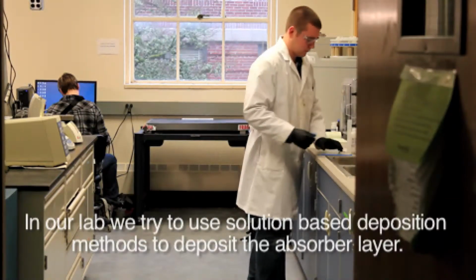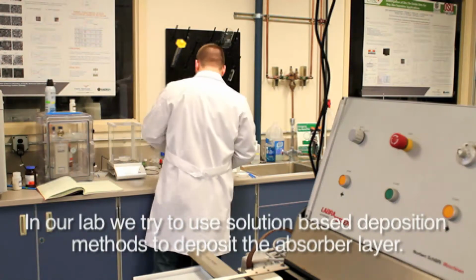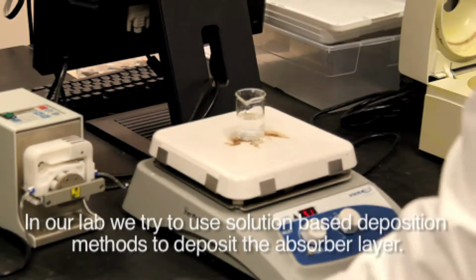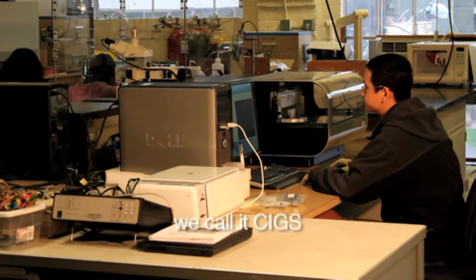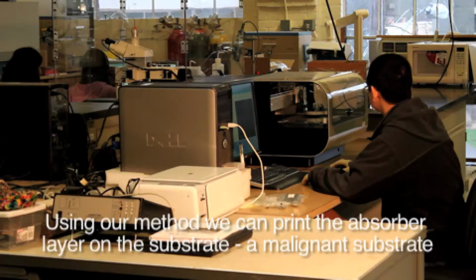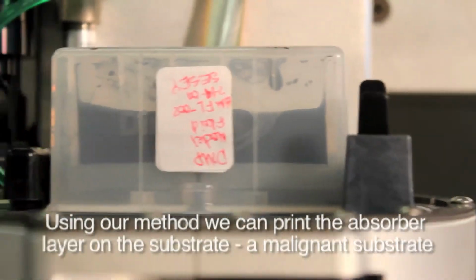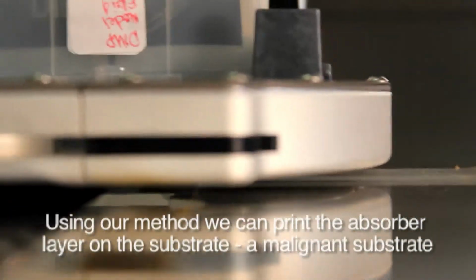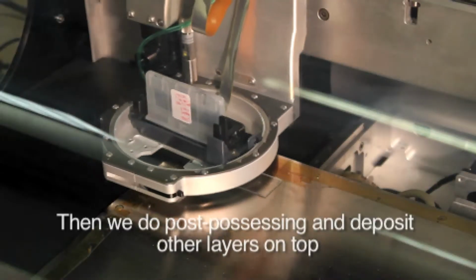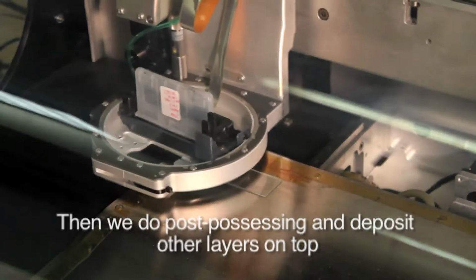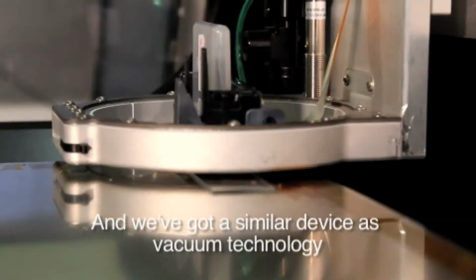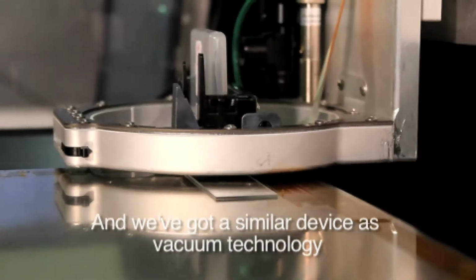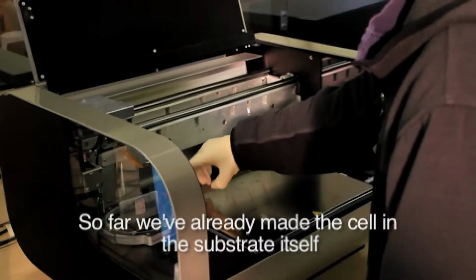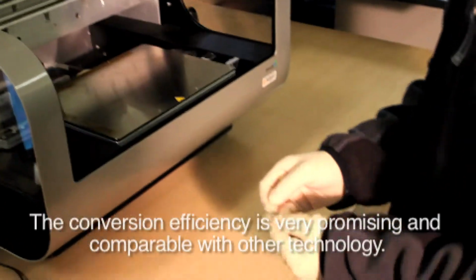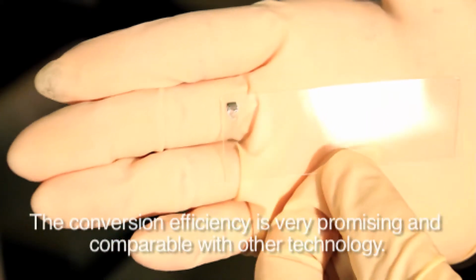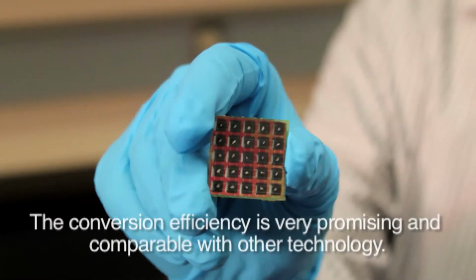So in our lab, we try to use a solution-based deposition method to deposit the absorber layer. We call it CIGS. Using our method, we can print our absorber layer on the substrate, a molybdenum substrate. Then we do some post-processing and deposit other layers on top. Then we get a similar device to vacuum technology. So far, we have already made the cell on the substrate itself. The conversion efficiency is very promising and comparable with other technology.